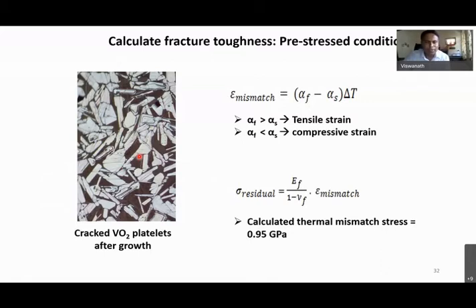Then we thought, okay, maybe this is the reason; the epitaxial thin films paper published in PRB also sees cracking happening. So we thought thermal stress was probably playing a role. Taking the VO2 thermal expansion and the quartz thermal expansion, we estimated the thermal mismatch and the stress. The stress is found to be around 0.95 gigapascal of tensile stress. So this is probably already a pre-stress condition.